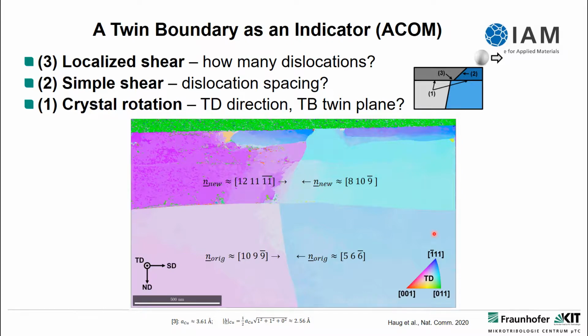Without going into too much detail, because I see I'm going a bit long here, but I hope you bear with me, the main result is that we have a misorientation between the ideal normal vector for a twin like this in copper and the one we get experimentally, somewhere between 2 and 5 degrees. There's not a big difference between below and above the trace line. So we have a more or less ideal twin experimentally below the dislocation trace line, and after the simple shear above the trace line, we still have a nice perfect twin. By the way, it changes a bit above the higher dislocation trace line, the twin character gets a little lost, but that would be going into too much detail for now.